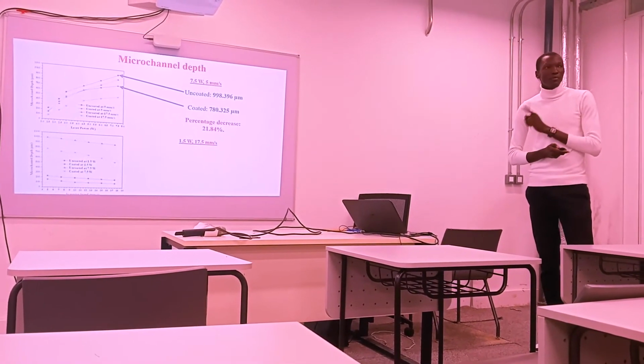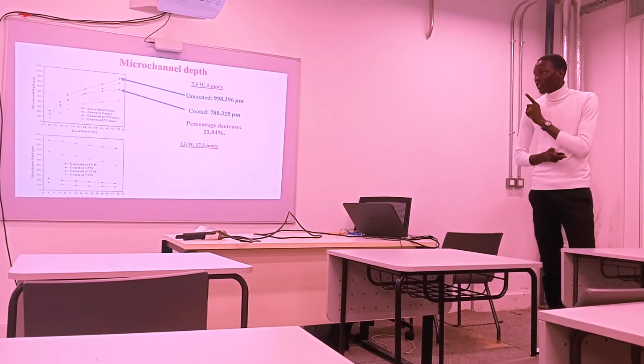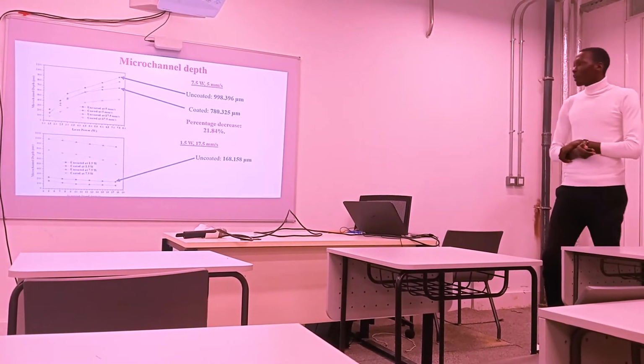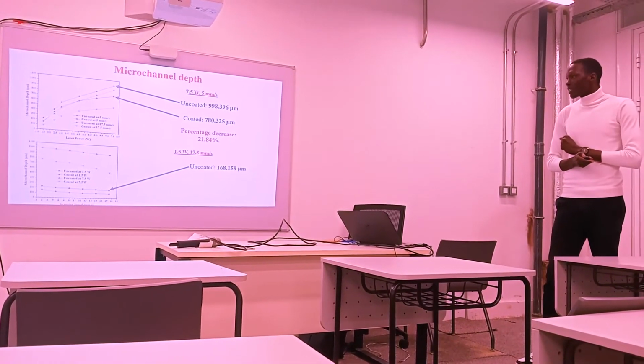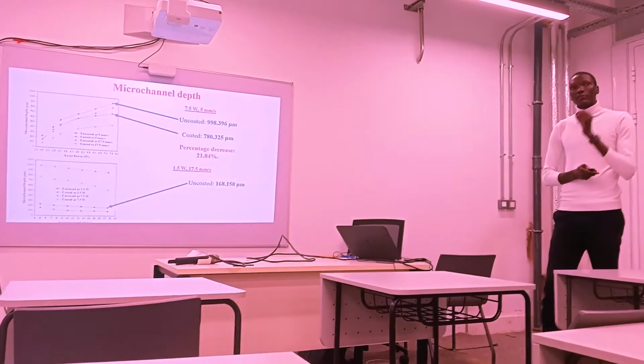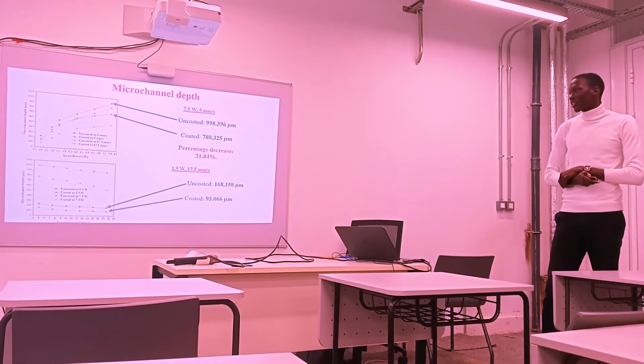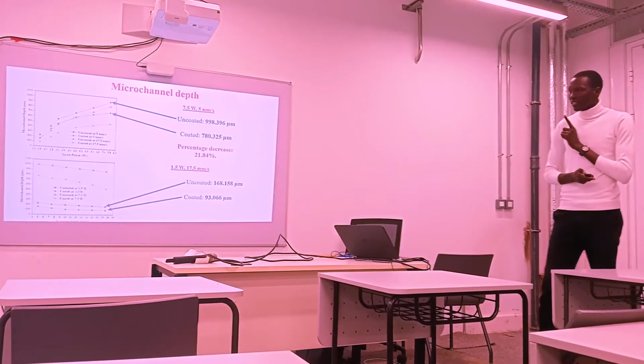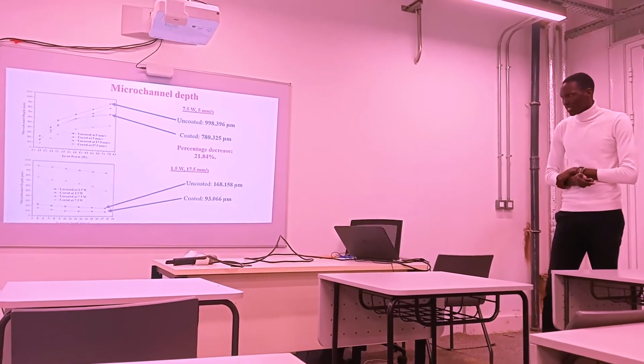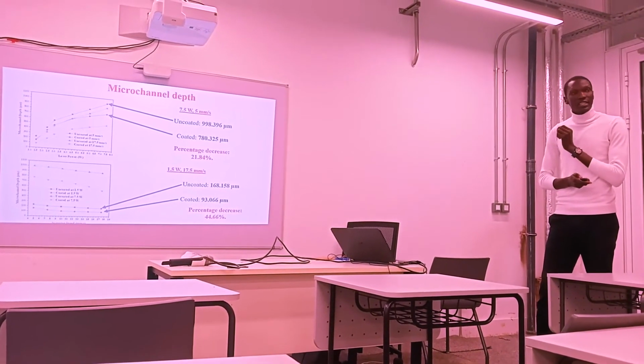Then, at the minimum power and the maximum speed, we got 168.158 micrometers for the uncoated, and then we got 93.066 micrometers for the coated, a percentage decrease of 44.66%.